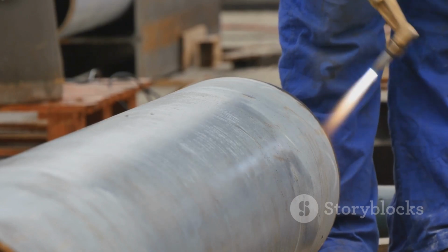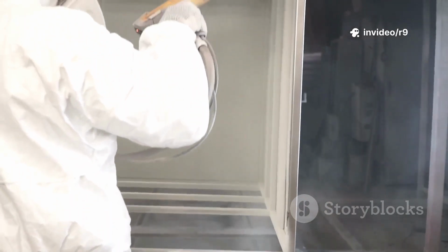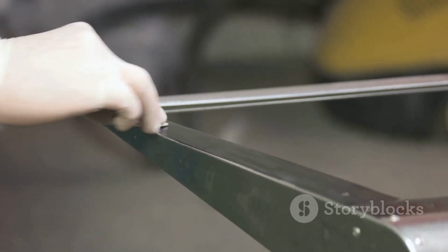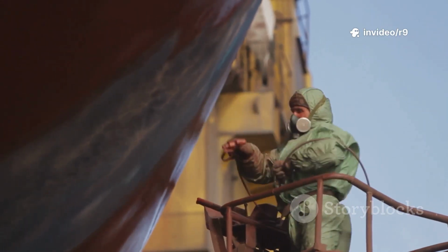But here's the catch. Surface preparation is critical. Blast cleaning, to SA3 standard, ensures proper adhesion. Because even the best paint won't stick to dirt and rust. And when it comes to epoxies, they're engineered to resist water absorption. Perfect for humid zones, splash areas, or marine decks.